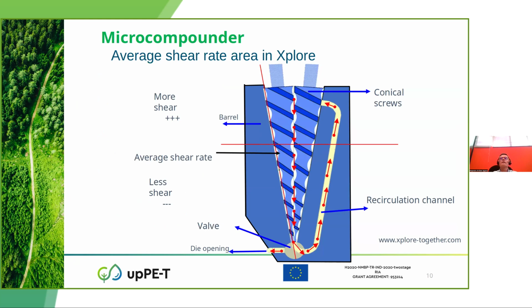Here with more detail, a high shear rate zone is present at the top of the screw, and the shear gradually decreases as the material moves along the lower part of the screws. We can increase the L/D ratio by recirculating the material through the recirculation channel. And once the mixture is homogeneous, we close the recirculation channel and remove the material through the die opening.